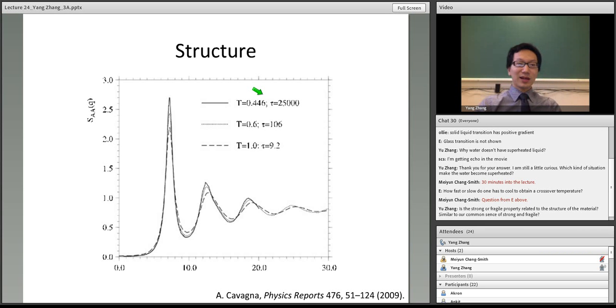So this is actually the most challenging question, or I'd say maybe the motivation to study supercooled liquids and the glass transition. How come the structure remains very similar, but the dynamics change by several orders of magnitude? In fact, the very influential mode coupling theory assumes that the structure factor doesn't change at all. But still, even if you keep the structure constant, by changing temperature or volume fraction, you can still find out why the relaxation time increases by several orders of magnitude.